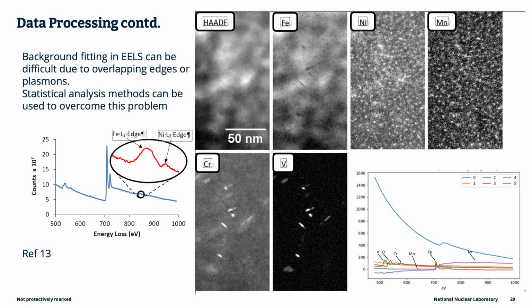In this particular case, this is another pressure vessel steel, I think. So the irradiation has produced more of these fine-scale manganese nickel precipitates. When the principal components analysis breaks down the potential contributions to a spectrum, this will be kind of the average, and then each of these is a different phase contribution to the eventual experimental spectrum. So one of them is a vanadium and chromium precipitate. One of the components has just manganese and nickel in it, and there's another one containing the oxygen signal.